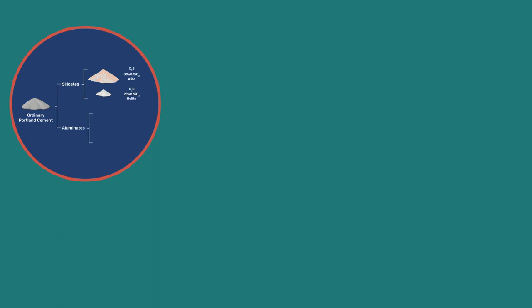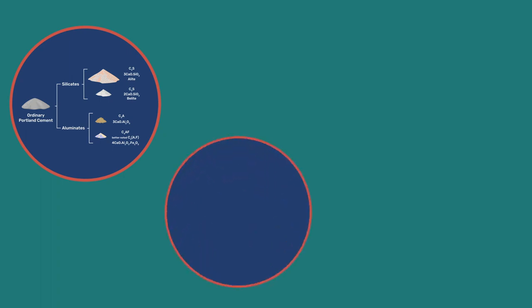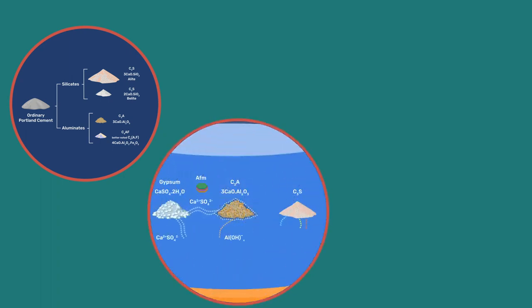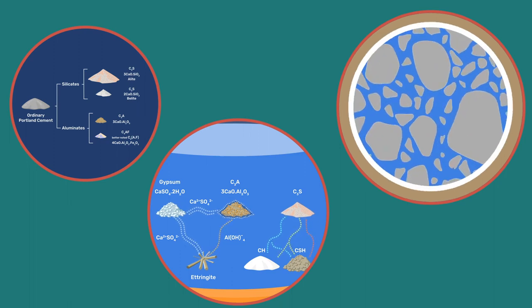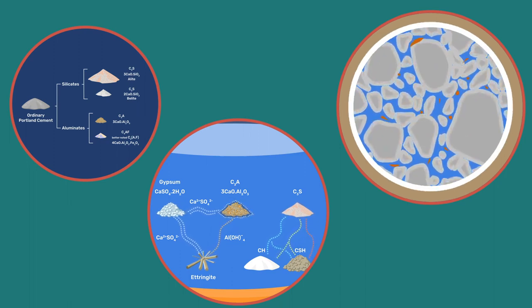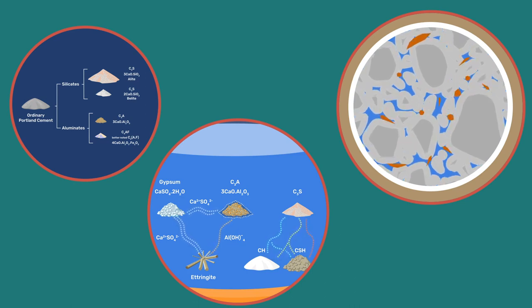In conclusion, ordinary Portland cement is a complex coupled chemical system in which two silicate and two aluminate phases react simultaneously but at very different rates. However, they do not do so independently, rather they influence each other through the ions that they release in solution. An illustration of this is the use of gypsum to prevent C3A hydration from passivating the hydration of C3S. In a well-regulated cement, C3S is responsible for strength and durability and has extensively reacted after a few days only.